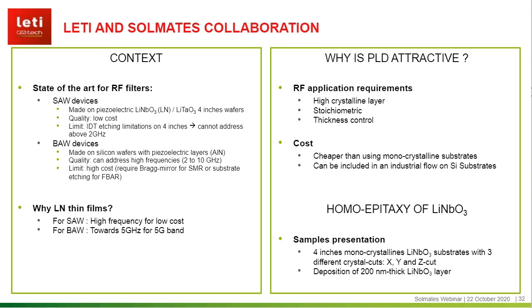The pulsed laser deposition technique is the perfect candidate for this, as the frequency applications require a highly crystalline layer, the stoichiometry, which is an important issue for piezoelectric lithium niobate, and finally, thickness control. Moreover, it could lead to the fabrication of low-cost resonators because it is cheaper than using monocrystalline substrates, and also it can be included in an industrial flow.